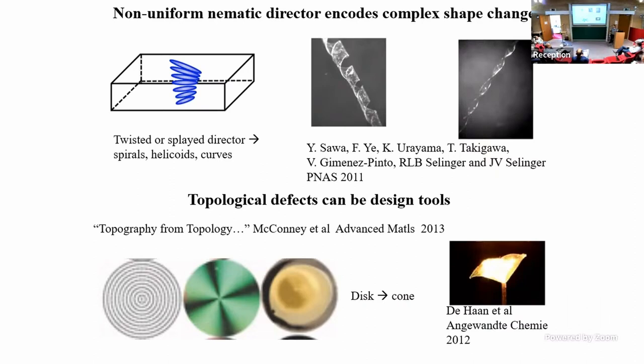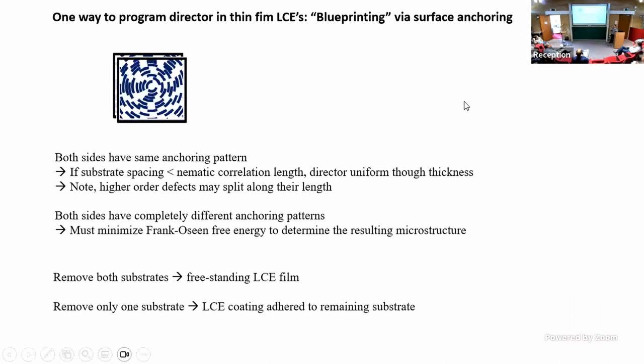So another way, I mentioned before, we can just do simple rubbing, but we can also pattern. So how do you get that target shape onto the nematic director? We're going to pattern two substrates with the topological defect. Here, the top and bottom substrates are identical, and that can be done a lot of different ways. One way is to coat the material with a monolayer of a material that orients in response to light, and then shine polarized light on it in a pattern to get whatever we want. But the key issue is if you put front and back, and then you take that away, you have the material with the nematic director uniform through the thickness because the front and back were the same. But the front and back don't have to be the same. We can have antagonistic anchoring conditions front and back and get a more complicated 3D director from that.